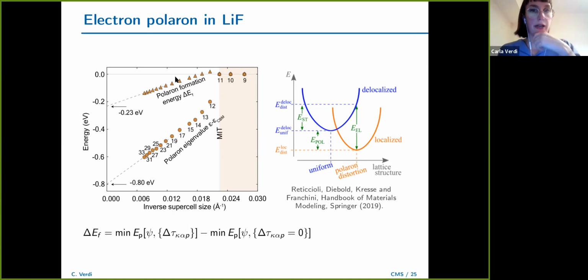You can see that actually these are energies versus the inverse supercell size. As I said before, the supercell size for us is the number of K points in our reciprocal space grids. But it doesn't matter because there's a one-to-one correspondence. So you see that for the case of an electron polaron in lithium fluoride, you would need supercells larger than 11 by 11 by 11, which is like 3,500 atoms, in order to achieve self-localization for your polaron.